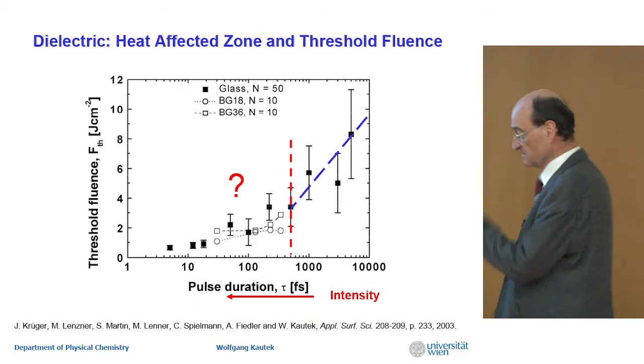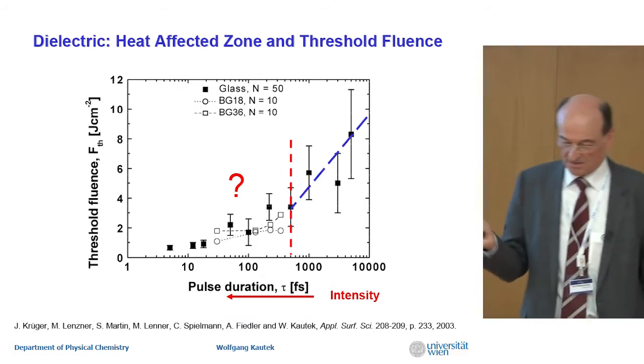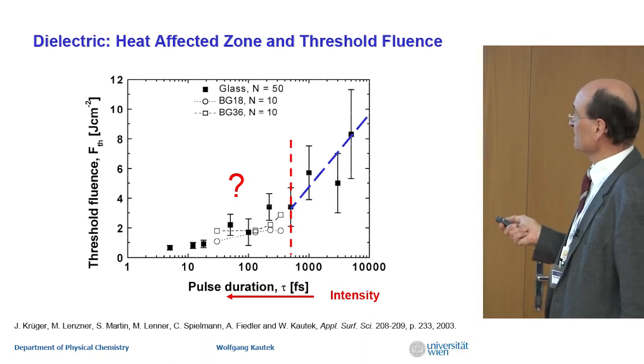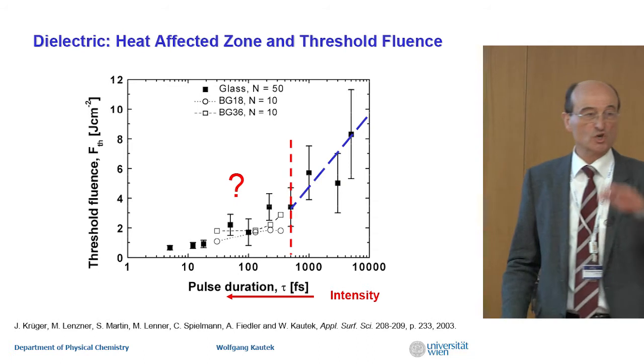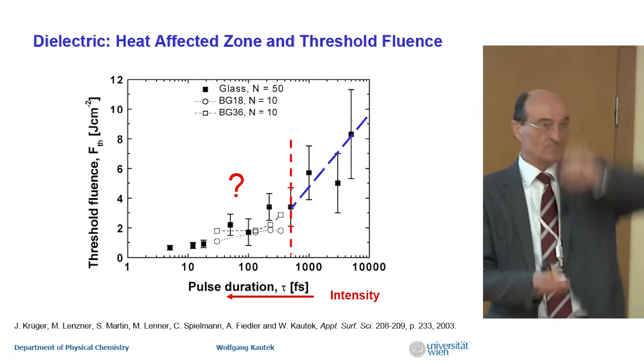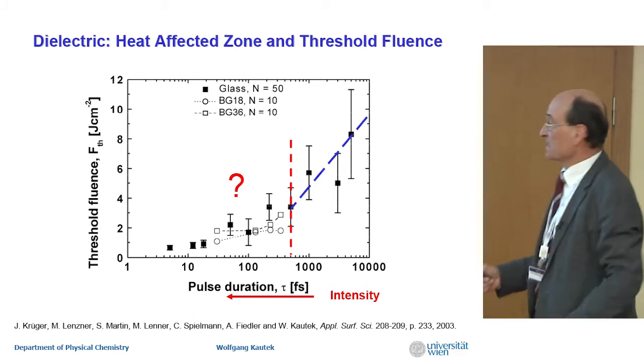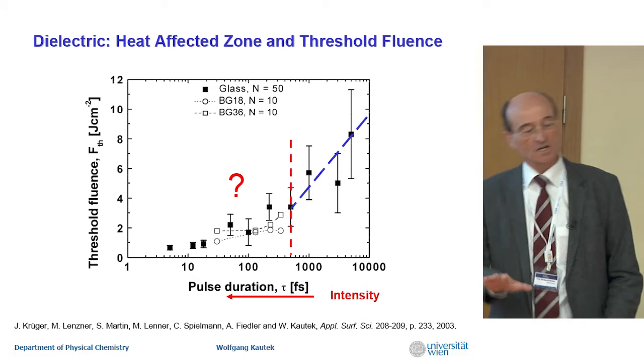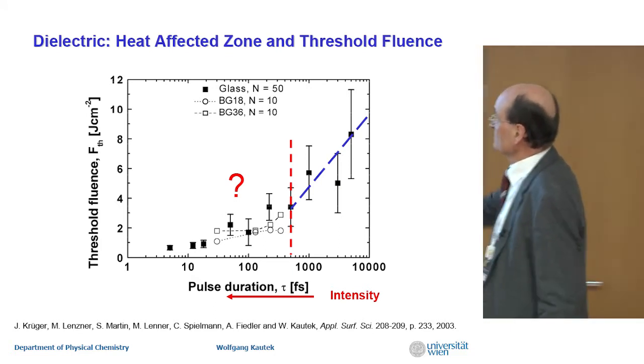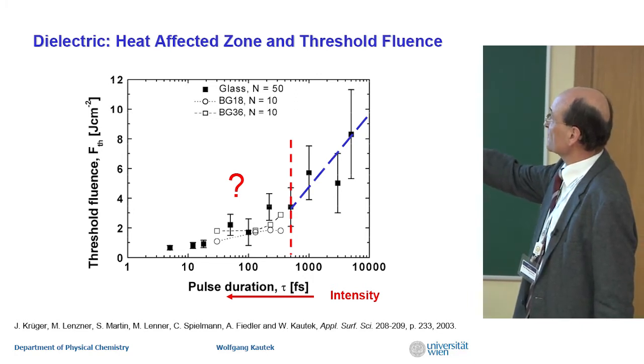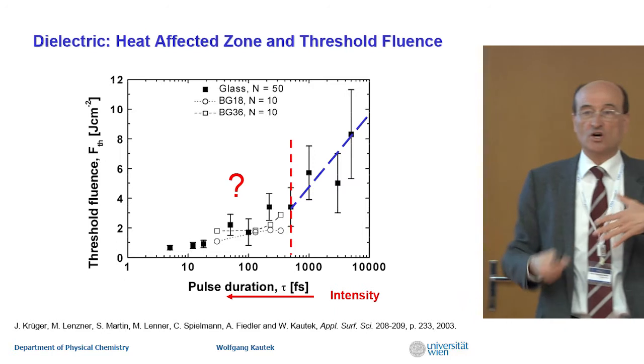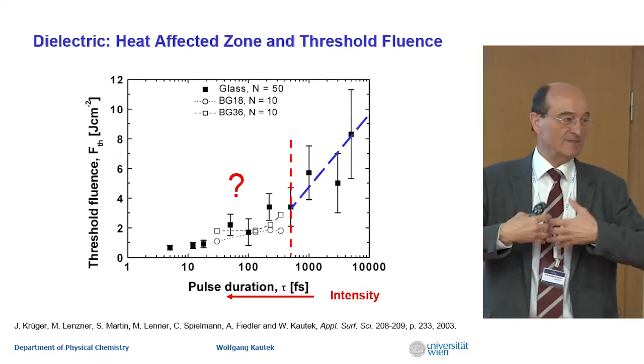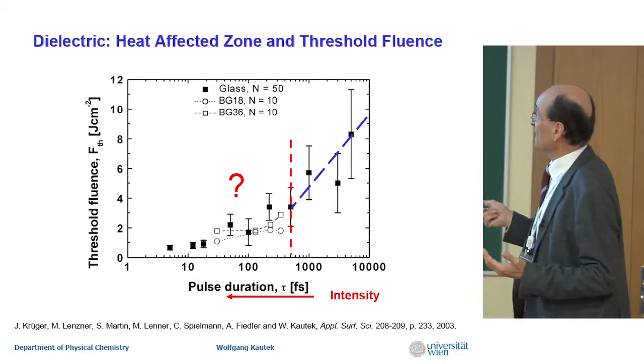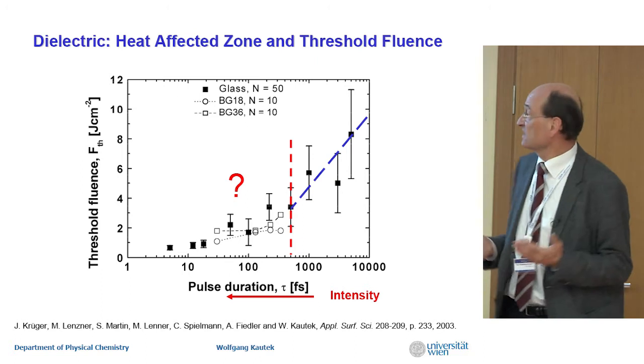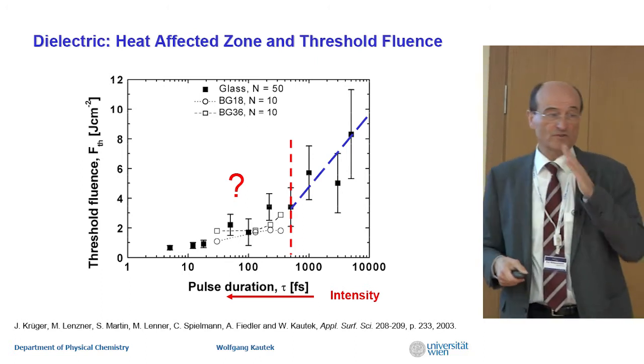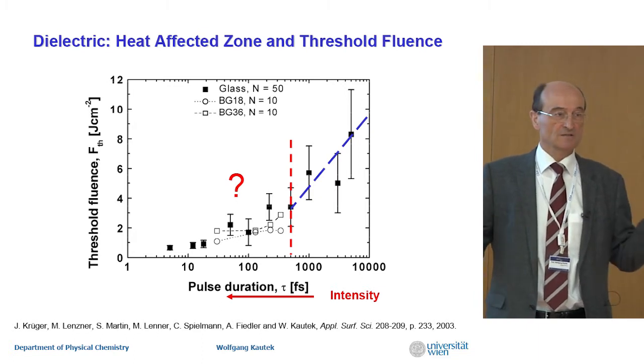So, come back to an experiment which gave us a lot of clues. You have the pulse duration. If you go to shorter pulses at constant energy, the intensity of the peak is increasing, yeah? The power. So, shortening the pulse means you can reach a high intensity at low energies. Now, here on the y-axis, there is the threshold fluence. What does the threshold mean? For a conversion of the material. In that case, it was the evaporation of a dielectric. So you see here, in this domain above the picosecond range, this follows a classical diffusional model.